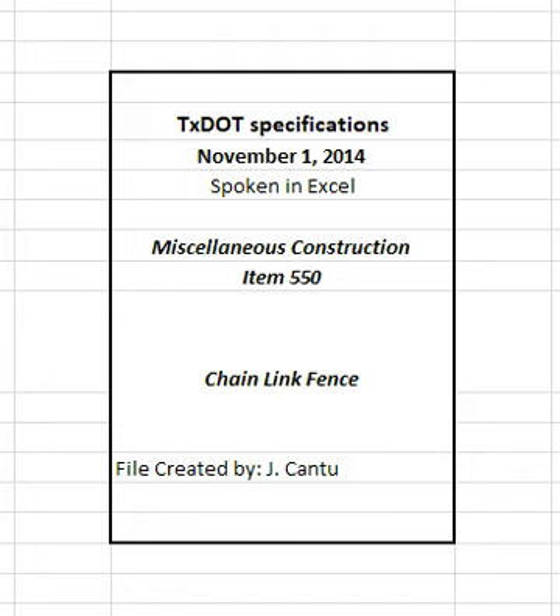2.15.1 Fabric. 2.15.1.1 Galvanizing. Hot dip galvanize in accordance with ASTM A392, Class 1. 2.15.1.2 Aluminum coating. Aluminum coat in accordance with ASTM A491. 2.15.1.3 Alloy coating. Coat with zinc 5% aluminum mischmetal alloy, Zn-5Al-MM, in accordance with ASTM F1345, Class 1.